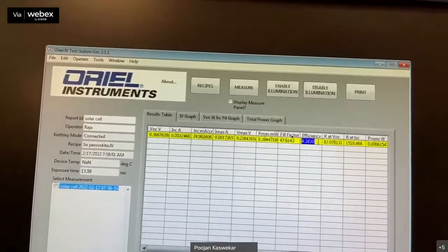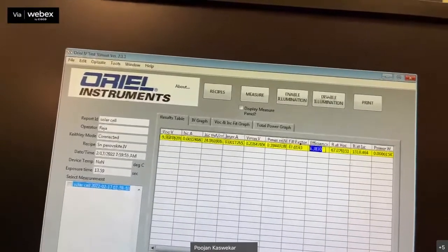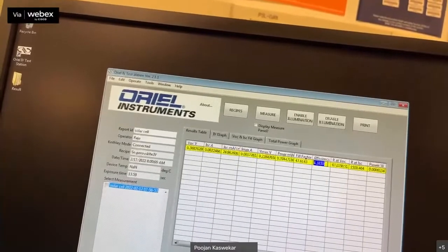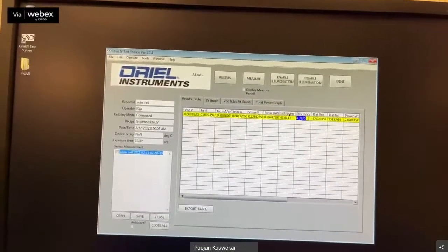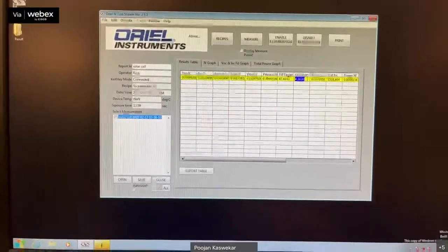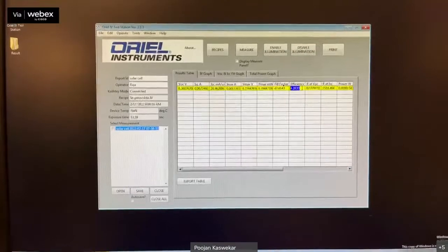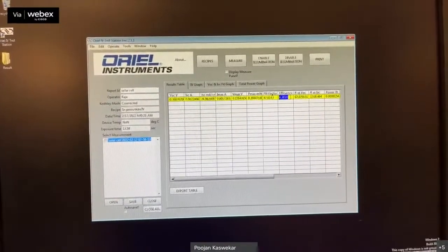I couldn't show you the 10 days before experiment because that's not in this system. We just took it away. So that decreased only by 0.3%, and this decreased by 1.6%. So now you know your doping is working properly. Then the next step is to prove why your doping is working properly. For proving that, we will do AFM, SCM, XRD, XPS. There are a lot of characterizations which will go on from here depending upon your doping.